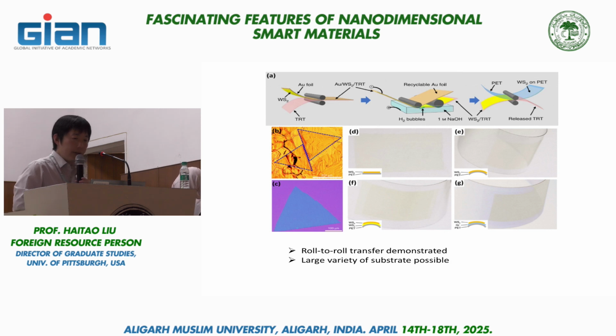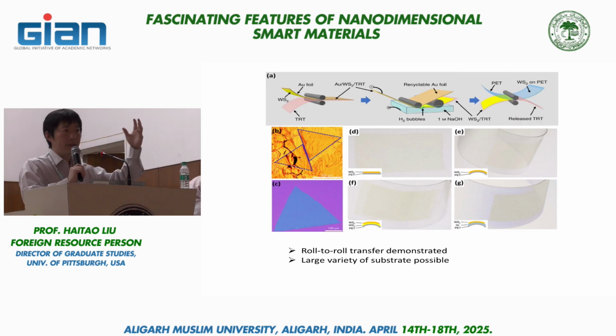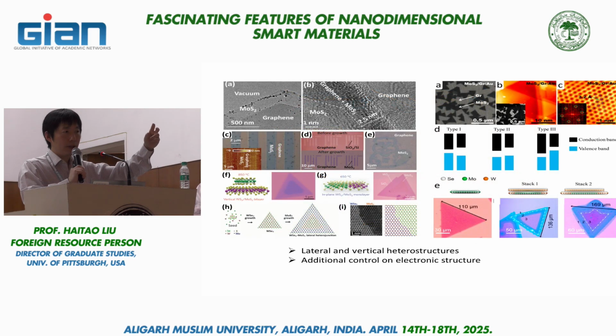Okay, so this technique can be expanded even further, and this is a very high density information slide, but it shows an expansion of this growth technique into heterostructures. Now, think about this whole process. This is the nucleation and growth. You bring in precursors, you will grow a little bit larger. Now, if you switch to a different precursor, you can have two different outcomes.